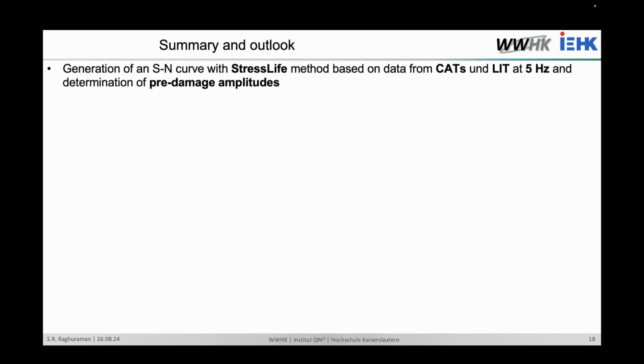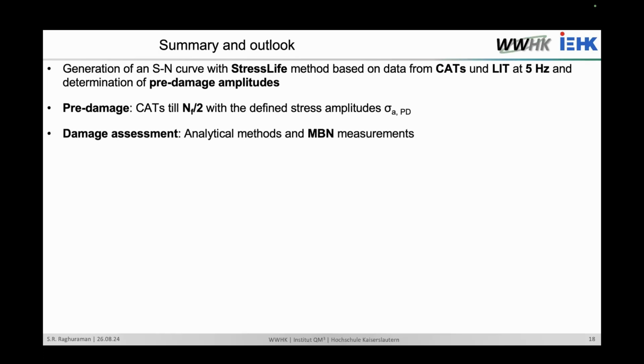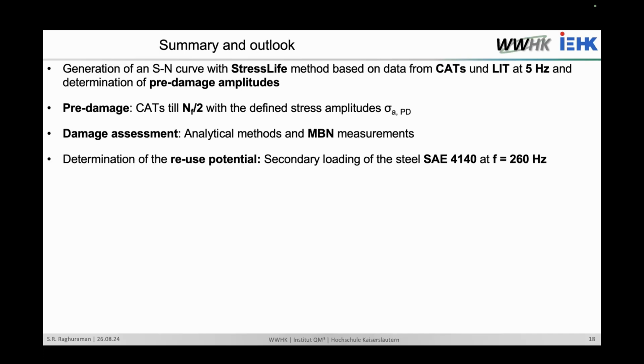So I'll come to the summary first. We started with the generation of S-N curves. Through that, we determined the pre-damage amplitudes and the extent of pre-damage that we are to introduce to the specimens. Then we carried out the pre-damage experiments till half of the lifetime. Then we assessed the damage that we had introduced onto the specimens. Then we loaded the steel for a second time at 260 hertz.